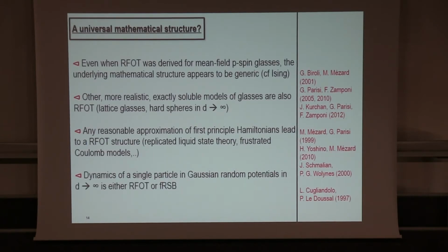And it's true that it's hard to think that there's such an analogy between models that are so different. But the answer to this, I think, is that what's remarkable about all this picture that I've shown you, in particular this fragmentation of the phase space, is that even if it was derived, as I said, in a very precise way on mean field p-spin glasses, the underlying mathematical structure appears to be very generic. It's a little bit like the Ising model, where we know that the Ising phenomenology is much broader than the Ising model itself. So for example, more realistic, exactly soluble models of glasses are also RFOT, like lattice glasses or hard spheres in large dimension, with the papers here. Interestingly, any reasonable approximation of first principle Hamiltonians leads to RFOT structure, like replicated liquid state theory, papers by Marc and Giorgio, and also Hajime and Marc.